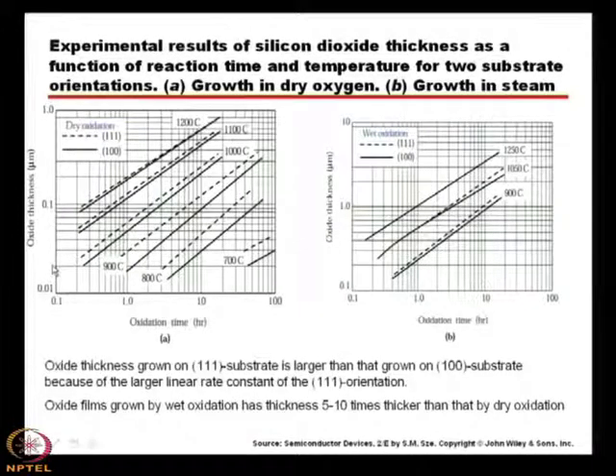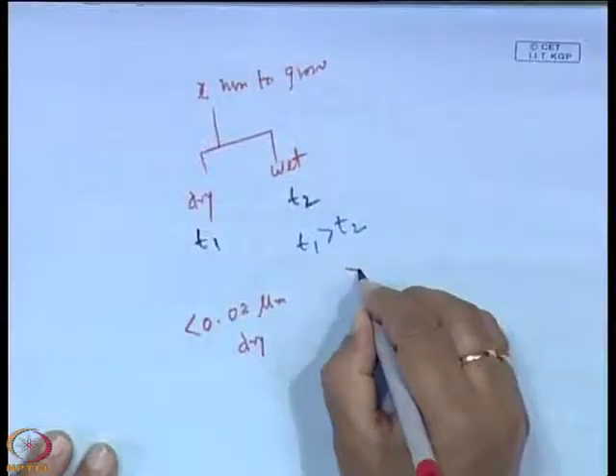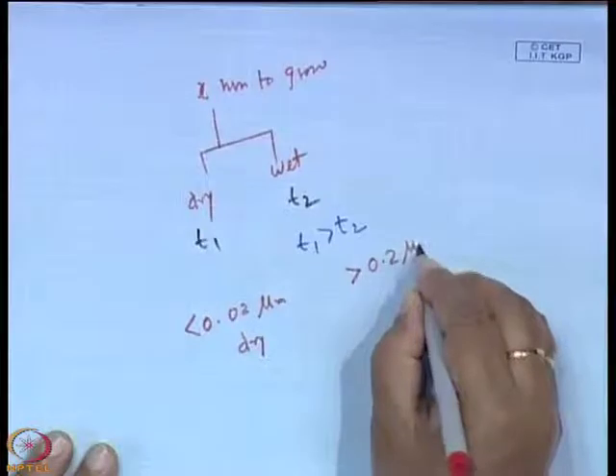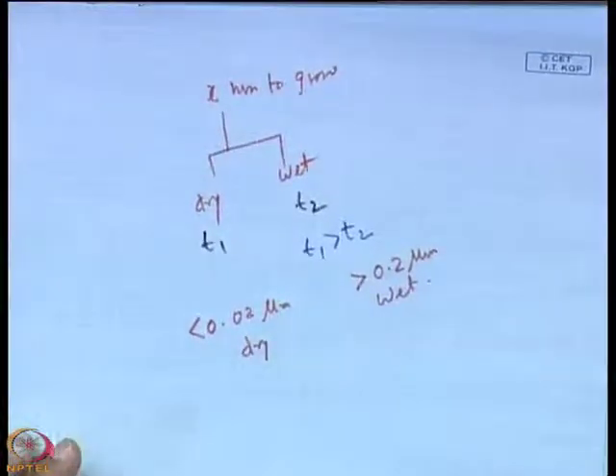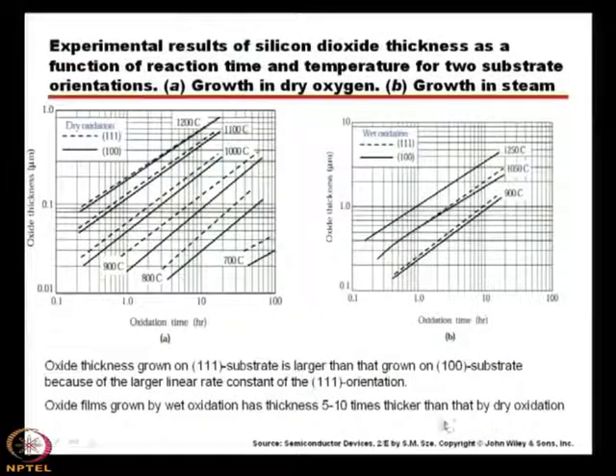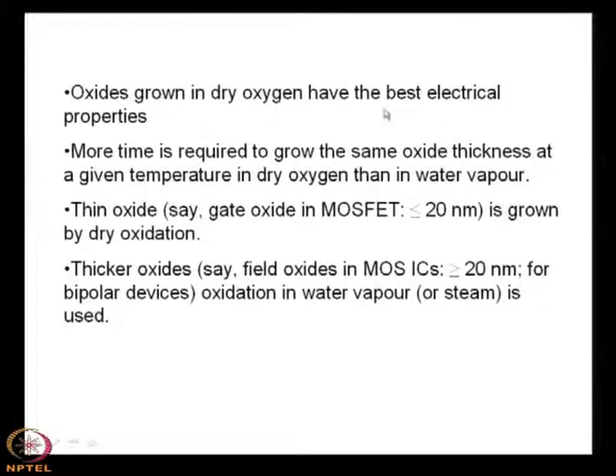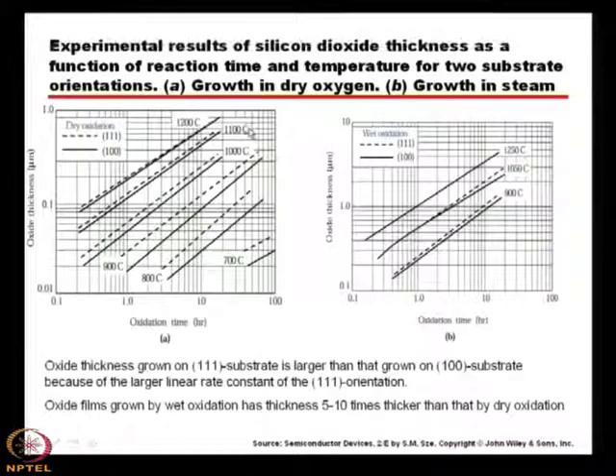So, it is less than 0.02 micron in case of the dry oxidation, whereas it is greater than 0.2 micron for wet oxidation. So, we can say that it is 5 to 10 times thicker than that by dry oxidation. However, this thick layer is electrically not the best one. Oxides grown in dry oxygen have the best electrical properties.